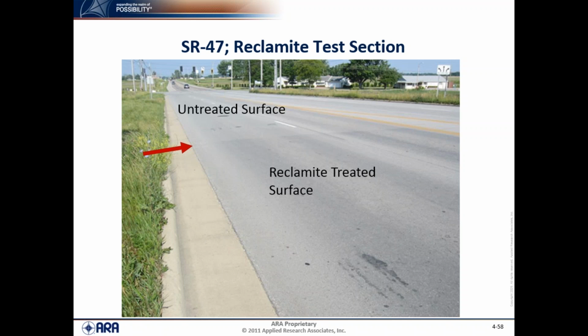On the other treated sections, the ones with bio-restore as well as replay, I don't want to say that there was no difference in the colors between the untreated transition section and the treated sections, but it was definitely much more difficult to distinguish. And that may be because they just started spraying, and whether that had a difference, I don't know. But for these, there was a definite difference in transition that you could still see for all projects, even 4 years after performance.